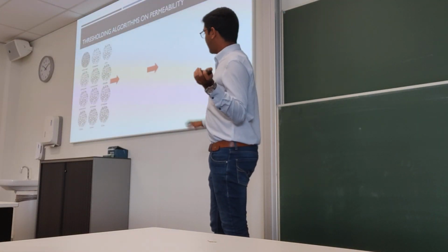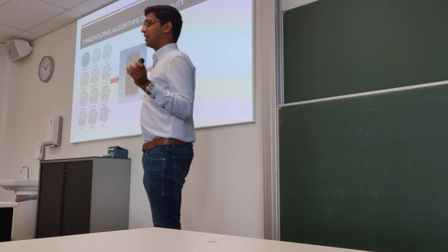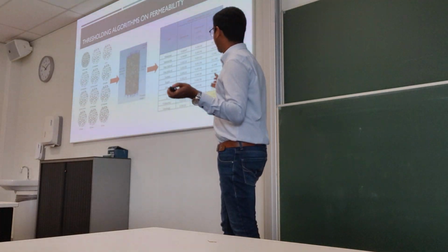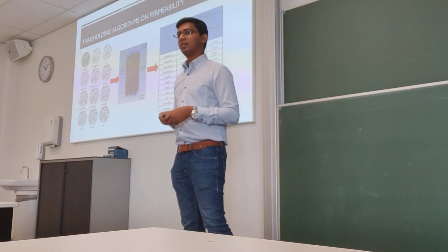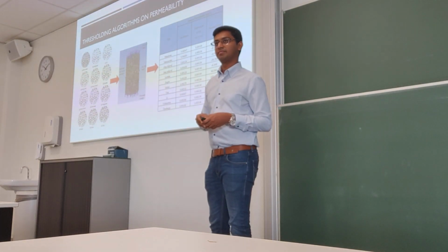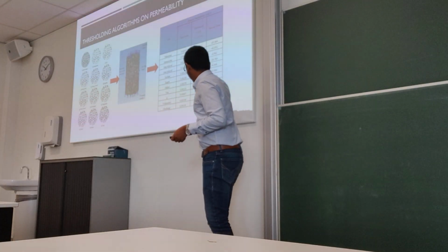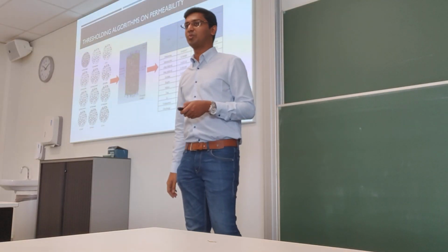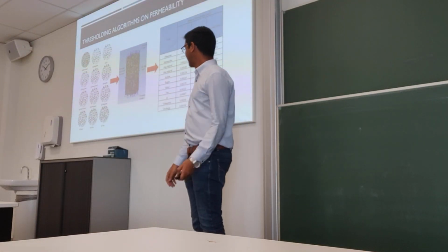So this is what my PhD is about: using each algorithm, feeding it into the computational fluid dynamics, and trying to find out the error percentage. When we did this, we found that the error can be as significant as 136%. So we proposed a small algorithm, which was producing less than 2.5% error. People were accepting this new algorithm, and our focus is again on accidents.